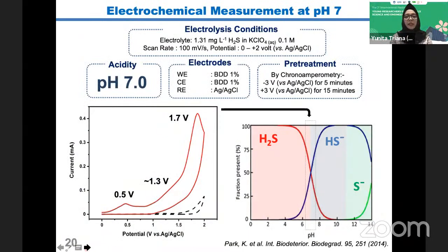Next, first I check the signal at pH 7. In electrochemical measurement, we care about pH because pH can give different behavior. At pH 7, I got three signals: at 0.5, 1.3, which is a broad potential, and also 1.7. And based on this graph from this paper, at pH 7 there are two species: H2S gas and HS minus.